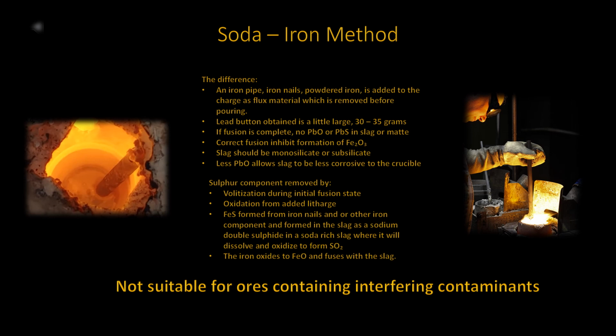When the fusion is completed, the slag and any matte formed should be free of any traces of lead oxide or sulfides. It takes a slow fusion, an excess amount of reducing agent, as well as a reducing atmosphere, which is required to inhibit any formation of Fe2O3, which is iron(III) oxide. This is an artificial form of hematite. The slag itself should be monosilicate or subsilicate. More about this classification later. However, the main ingredient of this slag would be soda. Due to the lack of lead oxide, the slag will be less corrosive to the crucibles.